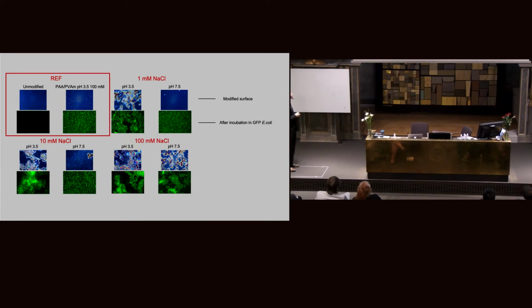And then we seed the surface with bacteria and visualize under fluorescent microscopy, and we can see that more bacteria are focused on this island or aggregate regions rather than the flat regions.